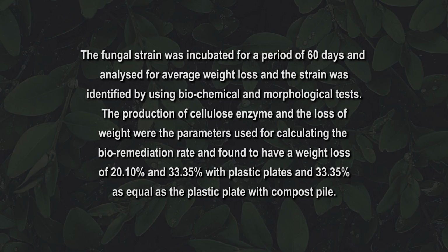The production of cellulase enzyme and the loss of weight were the parameters used for calculating the bioremediation rate, and found to have a weight loss of 20.10% and 33.35% with plastic plates, and 33.35% as equal as the plastic plate with compost pile.